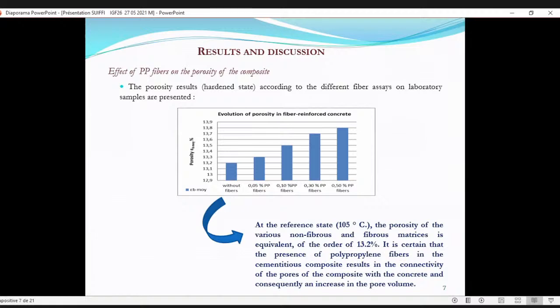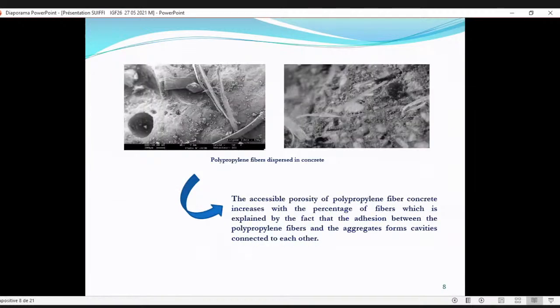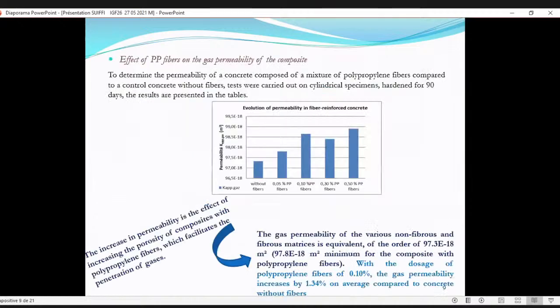As the reference states, the porosity of the various non-fibrous and fibrous matrix is of the order of 13.2%. It's certain that the presence of polypropylene fiber in the cementitious composite results in the connectivity of the pores of the composite and consequently an increase in the pore volume. Here we can see the polypropylene fibers dispersed in concrete, and we can see the cavities and the pores. The accessible porosity of polypropylene fiber concrete increases with the percentage of fibers, which is explained by the fact that the adhesion between the polypropylene fibers and the aggregate forms cavities connected to each other.